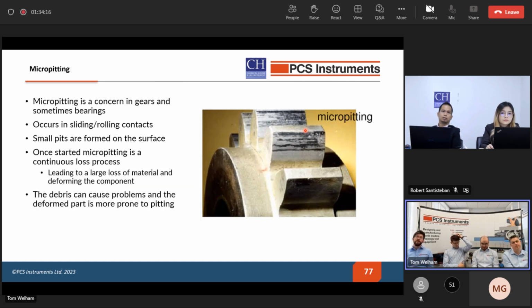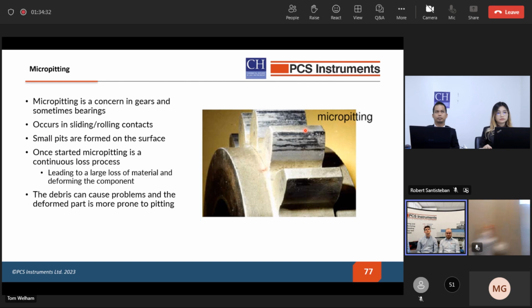Next, we'll talk about micropitting. So micropitting is more of a concern in rougher contacts and thinner films where you have a lot of roughness in contact, which creates all these very high stresses very close to the surface. It occurs in these non-conformal rolling sliding contacts, quite often in gears which have a rougher surface than bearings. So you can see here in this gear, we can see where micropitting is formed, where it's duller and matter than the rest of the gear flank.